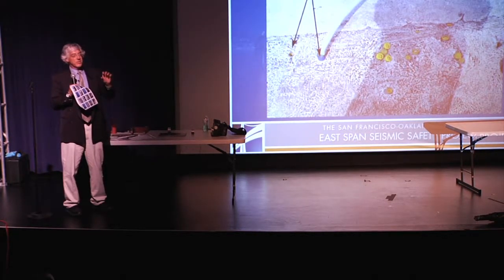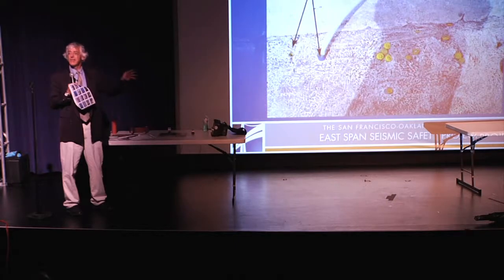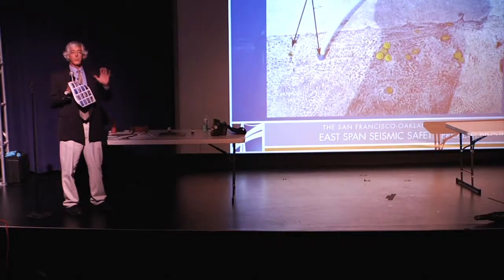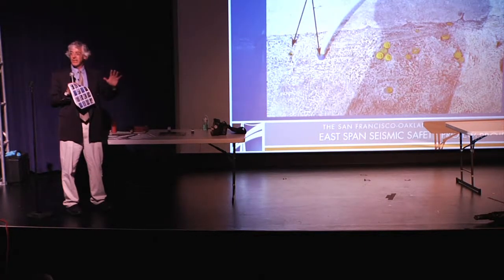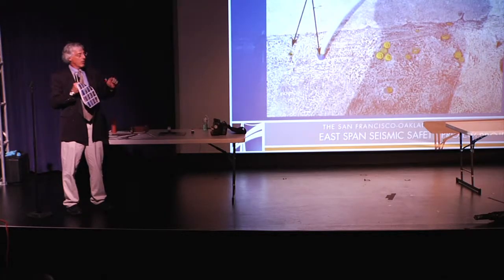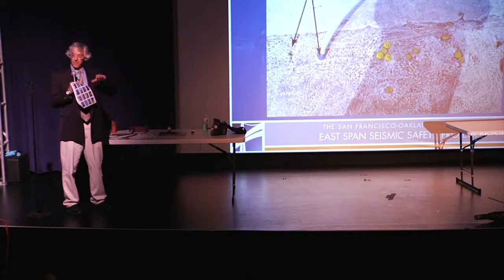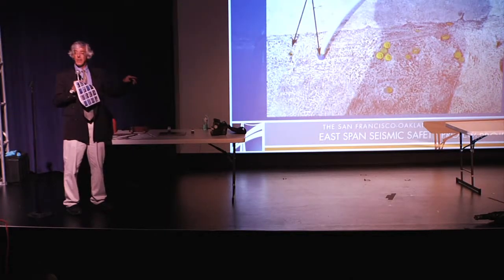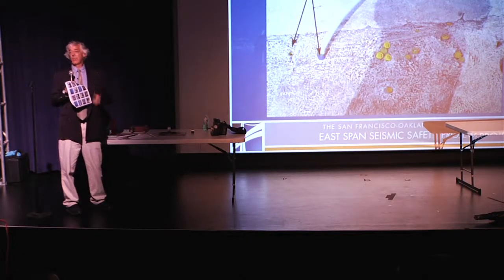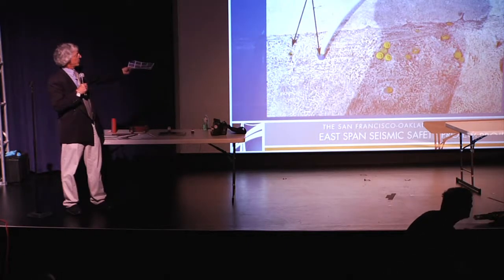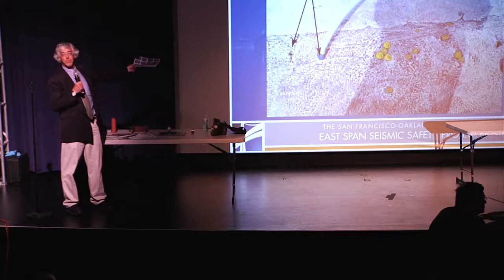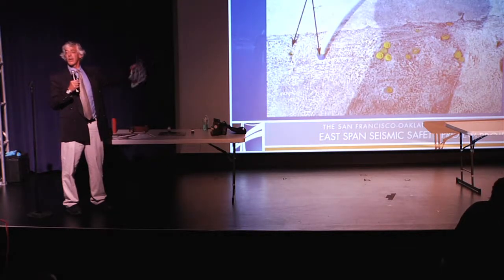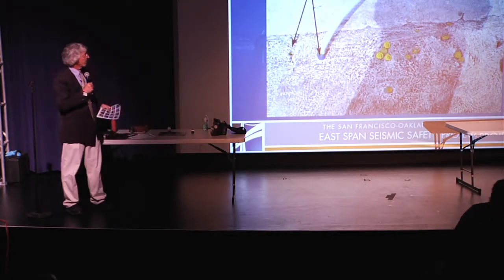The pre-stressing tendons don't completely fill those ducts. So once we're done pre-stressing and erecting the structure and loading it up, we actually fill those ducts with grout. We do it through the vents, but we also let the air out through those vents, and they need to be capped. What we found out was some trucks had probably run over them and they had broken off. And then when it rained, water got inside those ducts. Water and steel don't work very well.